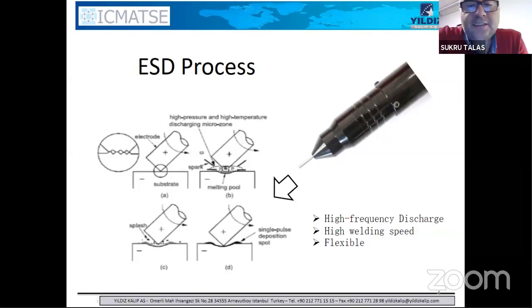So what is the ESD process? The ESD process is called low energy welding or low energy arc welding. You have an electrode that is continuously rotating. When it touches the surface, because there is an arc flow or electric flow, as soon as it touches the surface, it creates a small molten area. It's a melting pool, an arc pool, and with this arc pool, you alloy the surface with the electrode. As soon as you're done, that area solidifies and a newly alloyed surface is created.